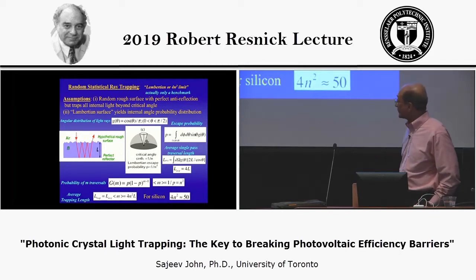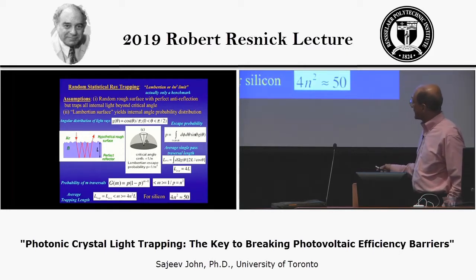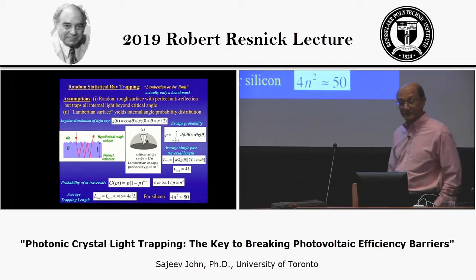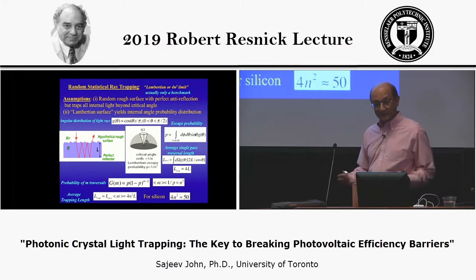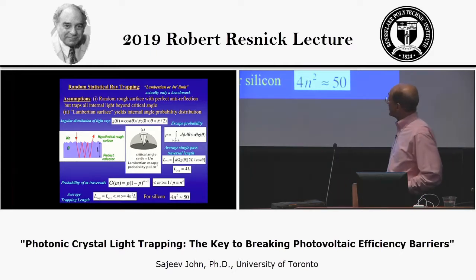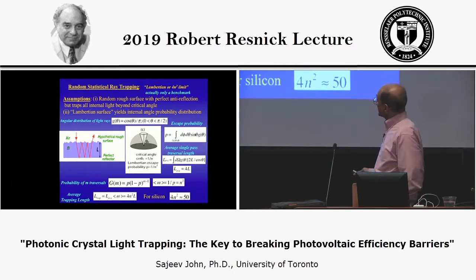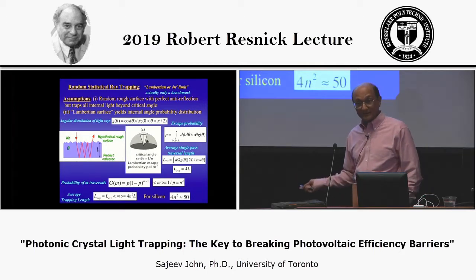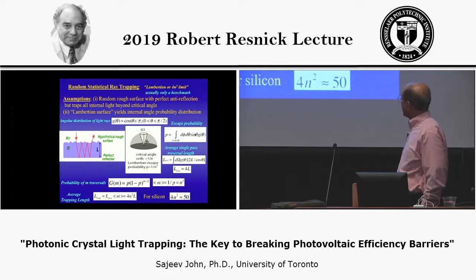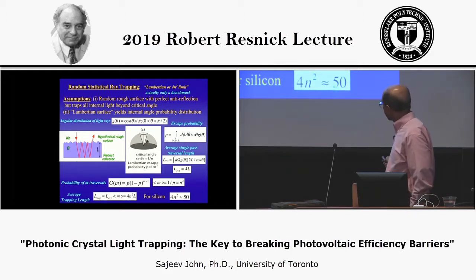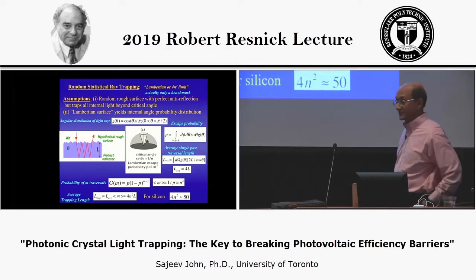It turns out to be 4 times the square of the refractive index times the actual thickness. So this has been a benchmark for defining what is a really good absorber and what is not. And so far, no real solar cell has actually managed to exceed this, what's called the Lambertian limit. In the case of silicon, the enlargement of the path length is by about a factor of 50, and that's what gives rise to these current efficiencies.